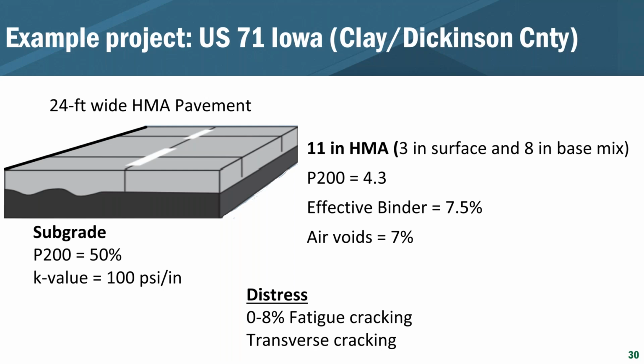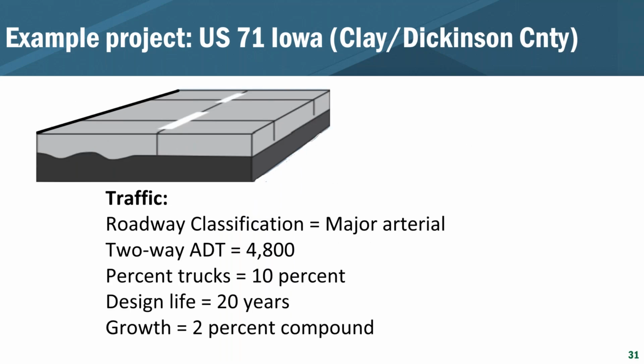And then regarding the mixture characteristics for the asphalt, the P200, percent fines passing the 200 sieve, was 4.3%. I apologize, I forgot my percentage there. The effective binder content was 7.5%, and then the air voids was 7%. So the distress that was exhibited based on the information they had was about 0 to 8% fatigue cracking. And then the transverse cracking was, of course, present as well, as you would imagine in the cold state of Iowa in the winter there. So that was the distress prior to coming in and looking at the design. Again, I'll mention the 24-foot wide pavement section, and we'll get back to that in a few minutes as well.